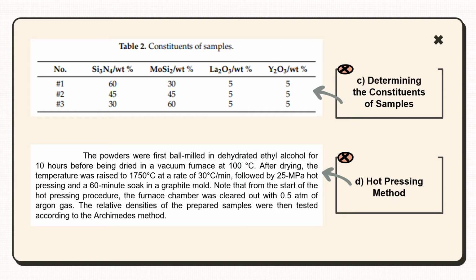After drying, the temperature was raised to 1750 degrees Celsius at a rate of 30 degrees Celsius per minute, followed by a 25 MPa hot pressing and a 60-minute soak in a graphite mold. Note that from the start of the hot pressing procedure, the furnace chamber was cleared out with 0.5 atm of argon gas. The relative densities of the prepared samples were then tested according to the Archimedes method.